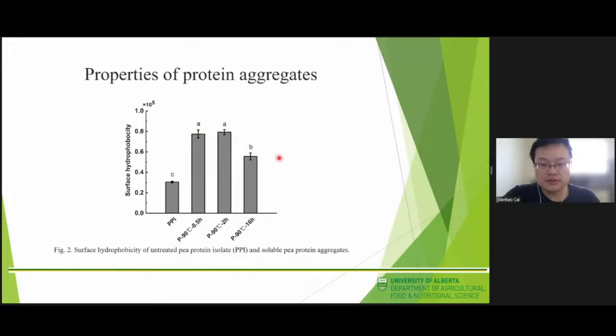Although the exposed surface hydrophobic groups formed hydrophobic interactions that played an important role in contributing to the protein aggregation, a significant amount of hydrophobic patches will still remain at the aggregate surface. The surface hydrophobicity of the protein aggregates decreased to a certain extent when the heating process was prolonged to 16 hours, because the elongation of the aggregates to form strands consumed some hydrophobic patches at the aggregate surface.